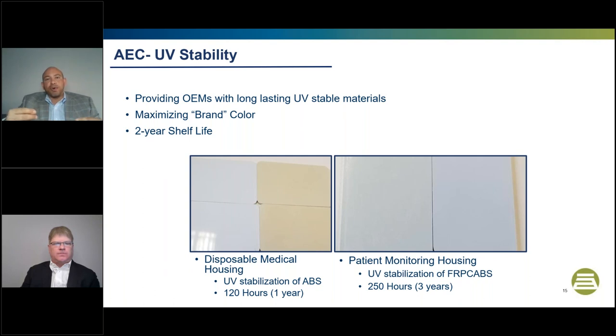Every 20 to 50 hours, we pulled the color chips out, hit them with a spectrophotometer, and took readings to show the color shift. This one, after 120 hours, was pretty easy to see. You can see how well UV stabilizing ABS does work, and that's representing a year's worth of UV exposure. On the right-hand side, it's a little harder to see.